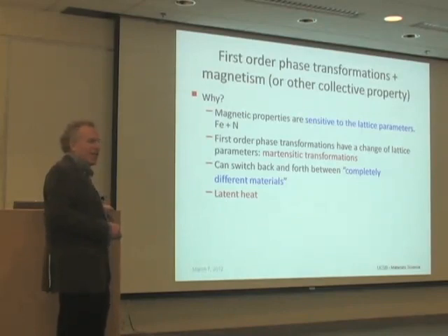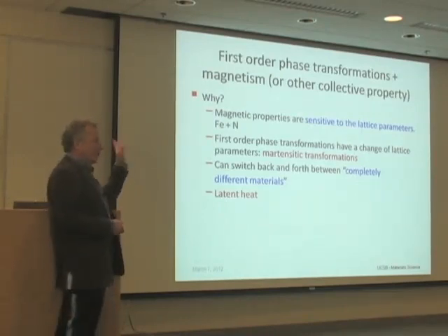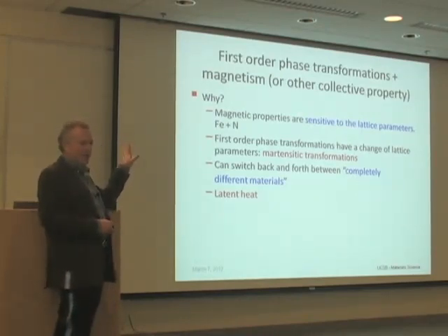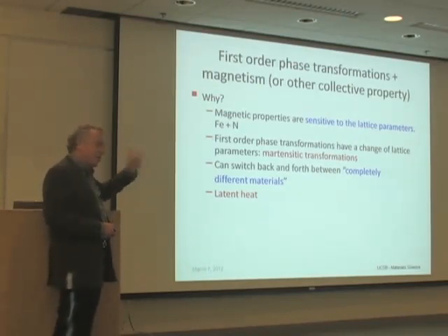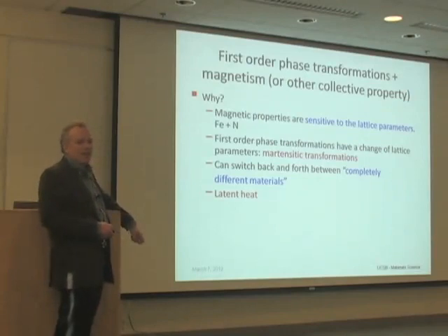There are many single phase materials, for example, a magnetic material near its Curie point, which can be made to have a large change of magnetization, but it absorbs negligible heat. So the latent heat part also plays an important role.